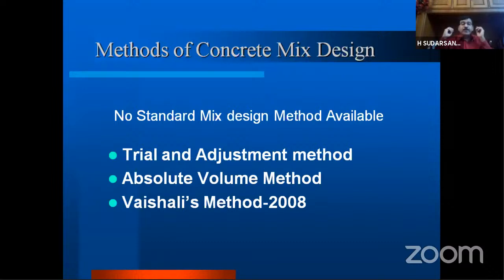In 2008, we proposed Vaishali's method, which we undertook as a doctoral research at JNT University, Hyderabad. This method is somewhat more rational, as in this method a relationship between the water cement ratio, the water binder ratio, and the various strengths of the concrete, the compressive strength, the tensile strength, and flexural strength, has been proposed. So as per this relation, you can choose the water binder ratio required to achieve the required compressive strength, or required tensile strength, or required flexural strength.